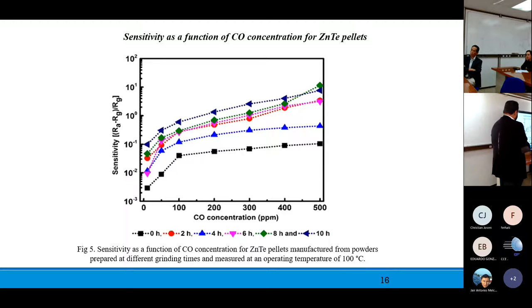We estimate the sensitivity as a function of the CO concentration for the zinc telluride pellets. And we can observe the sensitivity as a function of the CO concentration for the pellets at an operating temperature of 100 Celsius degrees. That was the best operating temperature condition that we saw in the last slide.